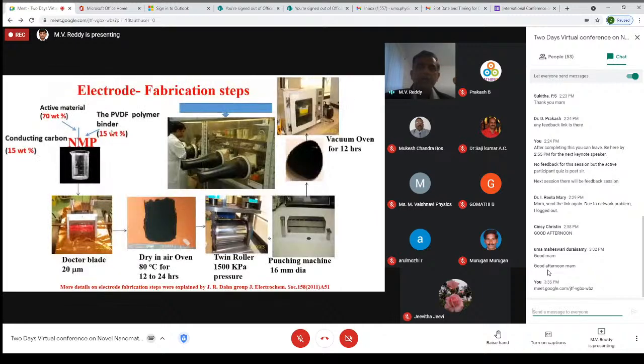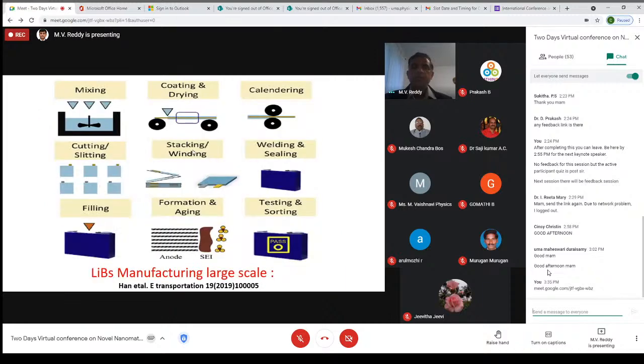This is the way we fabricate: you take active material, PVDF and carbon in 70, 15, 15. We disperse it in NMP, coat it with a doctor blade on copper or aluminum foil, depending on whether it is a cathode or anode, roll it and punch it. So the cell is ready, and we can press the cells. If you want to run at large scale in industry, I think everything is automated, so you don't need to do the work. For that, the technology only needs large-scale material.